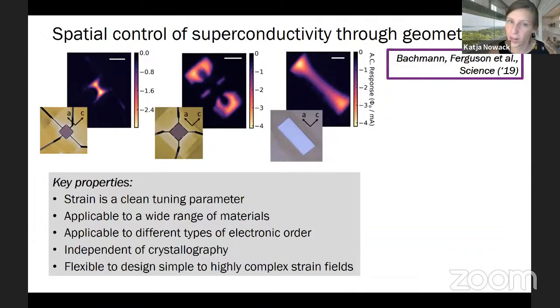But we also found a way to spatially control superconductivity, at least in a strain-sensitive superconductor, simply through geometry. This makes use of the fact that these microstructures allow you to create very complicated strain fields. And this is exciting because strain is a very clean tuning parameter. You do not chemically change your material. You could apply this potentially to a wide range of materials, essentially anything that is compatible with the focused ion beam.